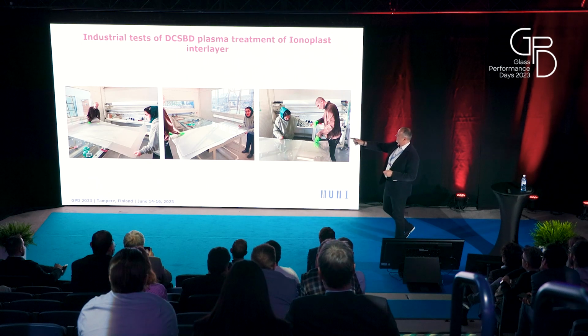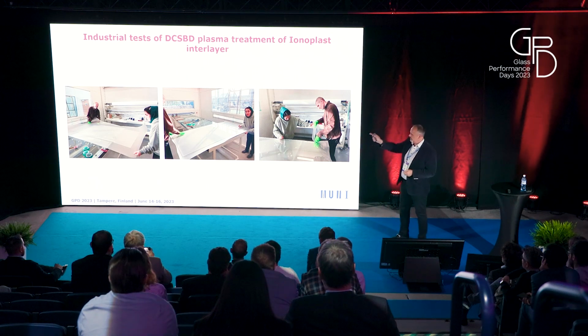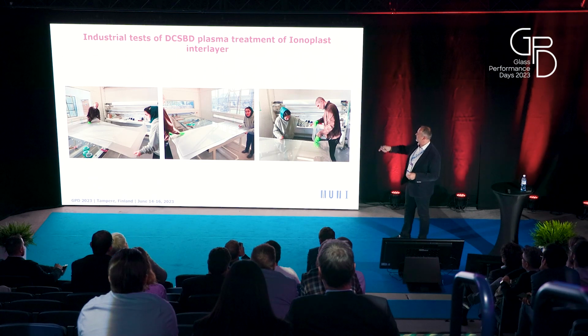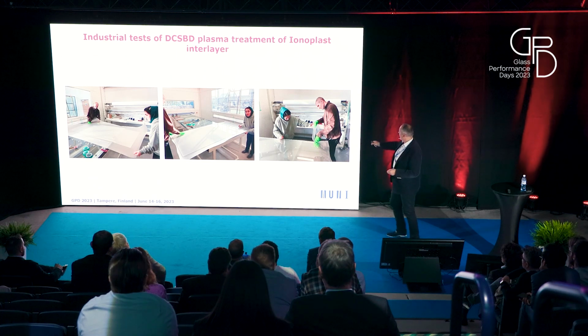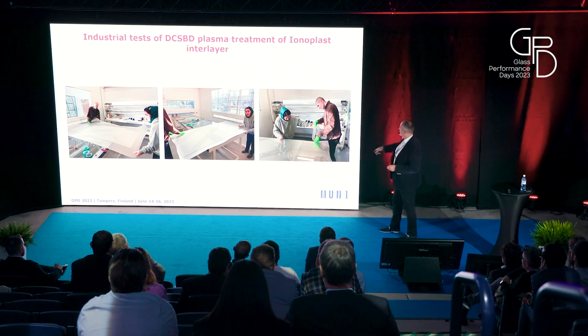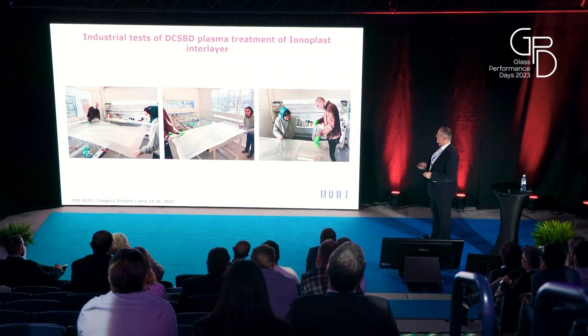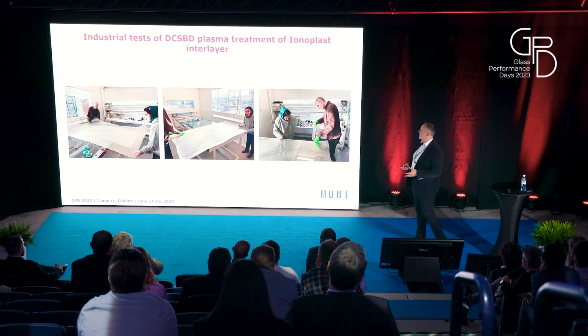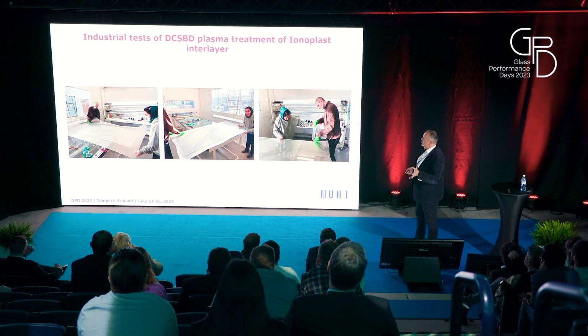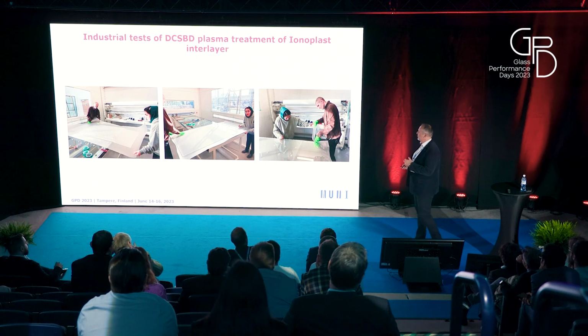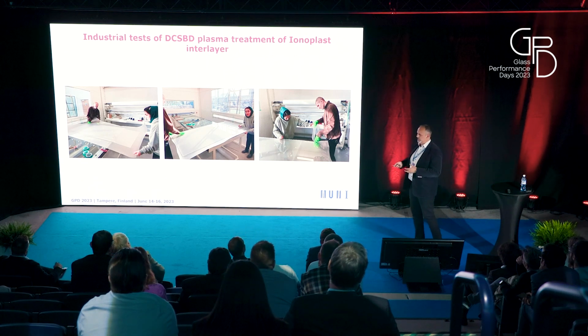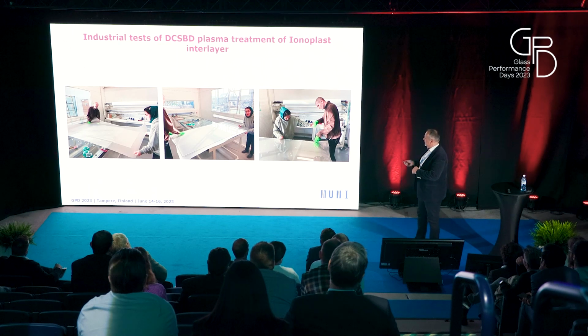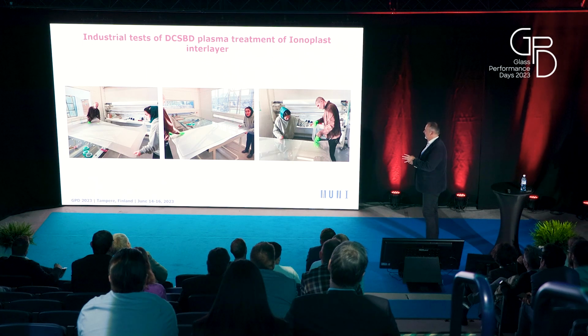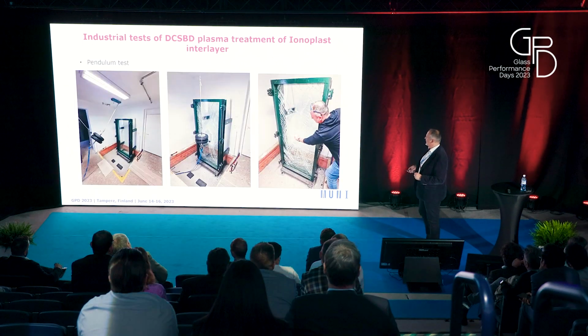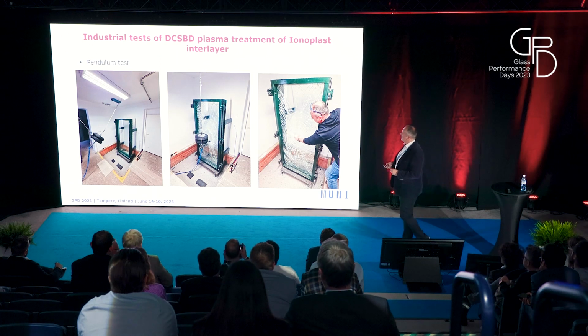On the first picture you can see activated SentryGlas which was put on the first plate, covered with the second one, and now the edges of the SentryGlas are cut away. We investigated different thicknesses of the glasses from 2 millimeters up to 8 millimeters, and also different combinations of the treatment. We compared using primer, we replaced primer by the plasma, we treated only glass, we treated glass and also the SentryGlas. This is the result of the pendulum test.